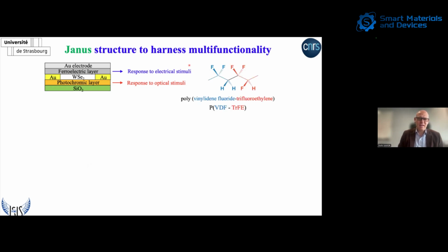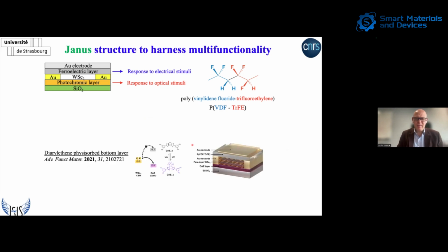We took the very interesting concepts that were brought to the community by Dago de Leeuw, who was at the Max Planck in Mainz together with Paul Blom, and Professor Azadi, who is now in the UK, by introducing the use of PVDF-TrFE, a polymer that is highly fluorinated. Upon applying an electric field, you can swap the orientation of the fluorine atoms, either pointing up or pointing down towards the interface with tungsten diselenide. And so they create a dipole at the interface, which can be used to accumulate or deplete the charges in the device. So that was more or less our device architecture.